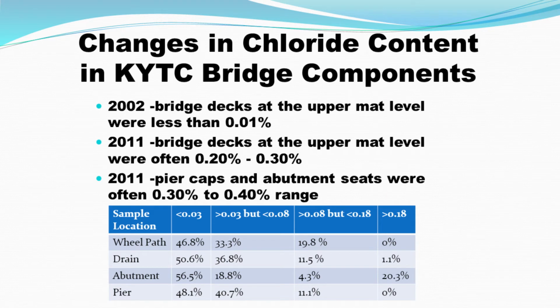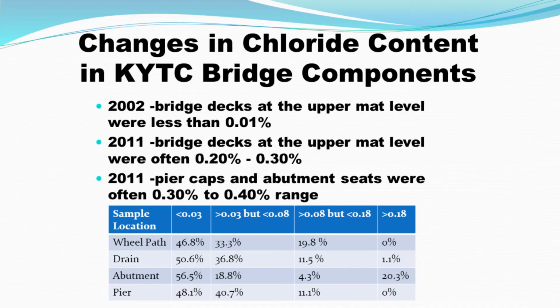This is the same graph that you just saw, only represented numerically instead of in graphic form. In the second column, less than 0.03, you have the abutment seats: 56% of all samples from the abutments were around 0.03. 18%, almost 19%, were between 0.03 and 0.08, so between initiation and accelerated corrosion. But look at the very last column, accelerated corrosion or major section loss at greater than 0.18 weight percent: 20% of the abutment seat samples are greater than 0.18% chloride by weight of concrete.